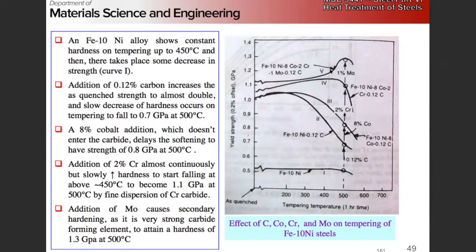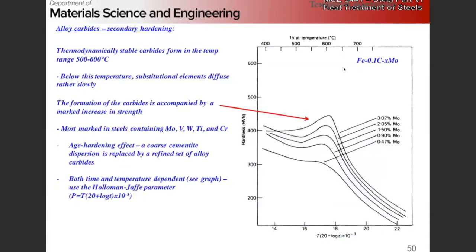Especially chrome and molybdenum are really going to lower the martensite finish. They're also going to push the nose over, right? So you'd have a much slower possible critical quench rate. Right. The idea is trends, right? Details are not as important, right?